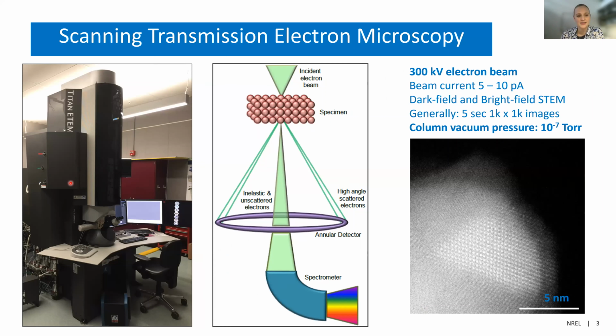In STEM, so scanning transmission electron microscopy, you have all of your electrons focused down into a probe, which you then raster over your sample, and then you're collecting the signal of either high angle scattered electrons that you're seeing over here, which create a Z contrast image so that the contrast scales with the atomic number of the elements in your structure, or you can get inelastically and unscattered electrons with a bright field image, or collect that with a spectrometer to look at energy loss spectroscopy, which will give you information about the bonding in your structure and also the composition. And then we sometimes pair it with X-ray spectroscopy up at the sample to look at heavier elements in your material.